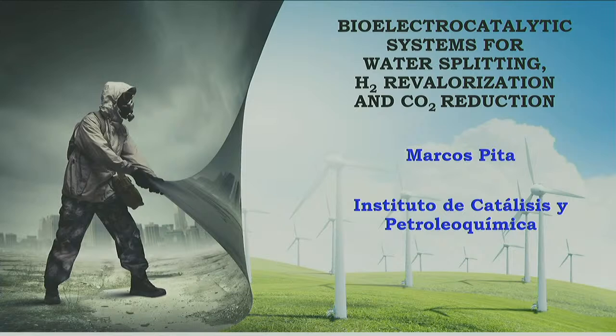Thanks to you. Marcos, how do you prepare the sulfide nanoparticles? It's chemical synthesis, and do you have a control on the size distribution, or does it have any effect in any case? Yeah. The most important factor here is not the size distribution of the particles, but the pore distribution. That's the most important part, and that is why the synthetic methods are solvothermal methods, and it has been a lot of optimization, research. We just come at the end of that.